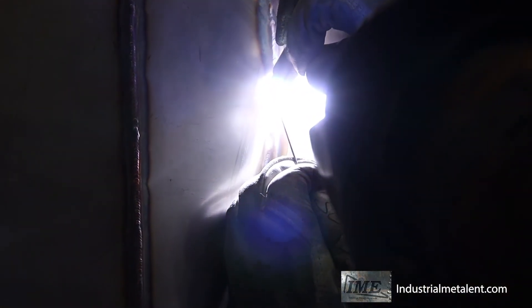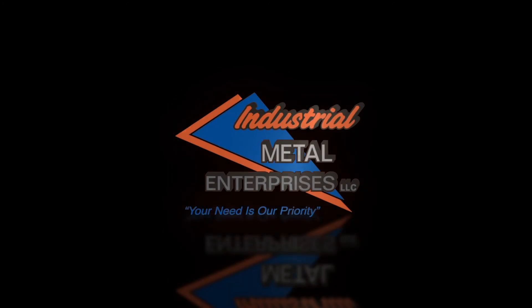A competitor was welding that, and I'm like, guys, they're doing it wrong. It's not going to work — it's going to have sugar and stuff. So I welded out a coupon and cut out the weld and handed it to the engineer. I said, this is how it's done properly — you go cut one of theirs out and it's going to have black sugar in it. And they did, and it did. They've got to purge that. And to this day — he told me, and this was probably about 15 years ago — he still has that coupon and shows everybody when they start talking about this. This is what we want.